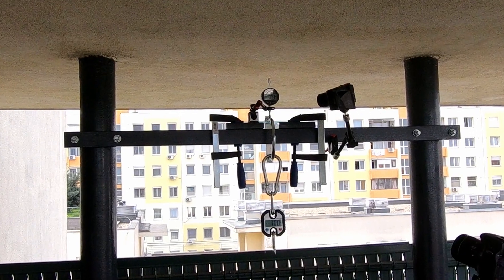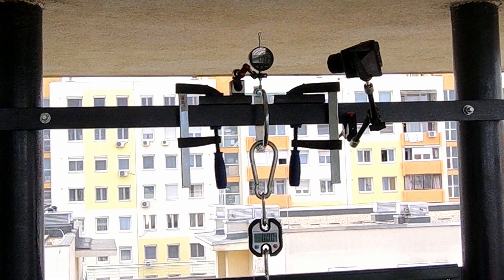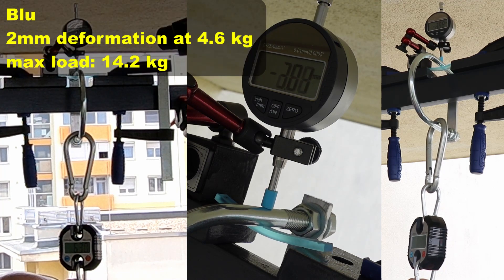This is my setup for three-point bending test. Distance between supports is 50mm, and the test is based on ISO 178. I am recording the load at 2mm deformation and the maximum load in kilograms.